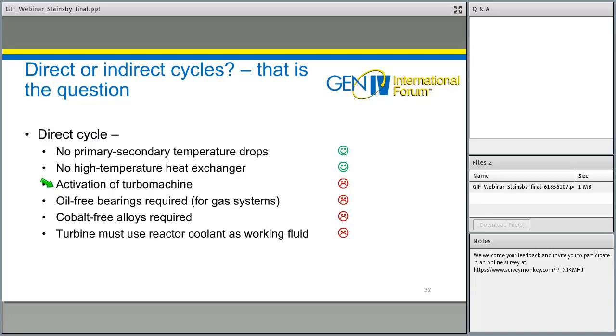We're putting reactor coolant through a turbine, and any corrosion products or erosion products which have been activated in the core will get deposited inside the turbine. And also, jumping ahead a bit, turbine alloys generally require a lot of cobalt for things like stellite hard facings or hot hardness for gas turbines. If we're going to put those in a reactor circuit, we've got to keep the cobalt out, because that becomes very radioactive if it passes through the reactor core.